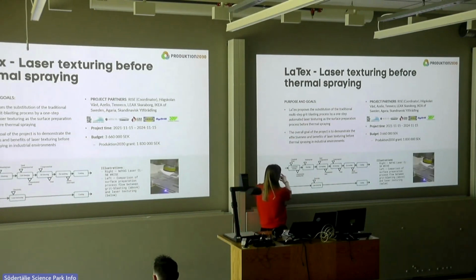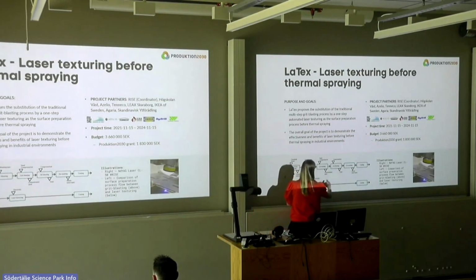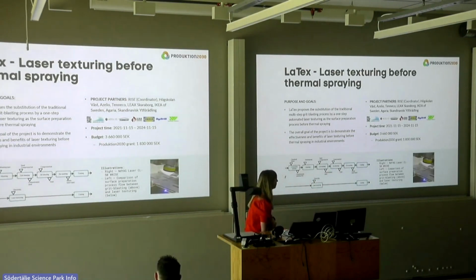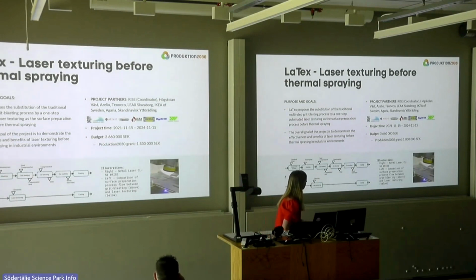When you have grit blasting, you have several process steps. You clean your component, do masking, grit blasting, and then you have to get rid of the grits, demask, and then you can do your thermal spray. And then we look at whether it is possible to replace all these steps with laser texturing. It's a project together with Högskolan Väst, Aselio, Teneco, Leax, IKEA, Agaria, and Scandinavia.